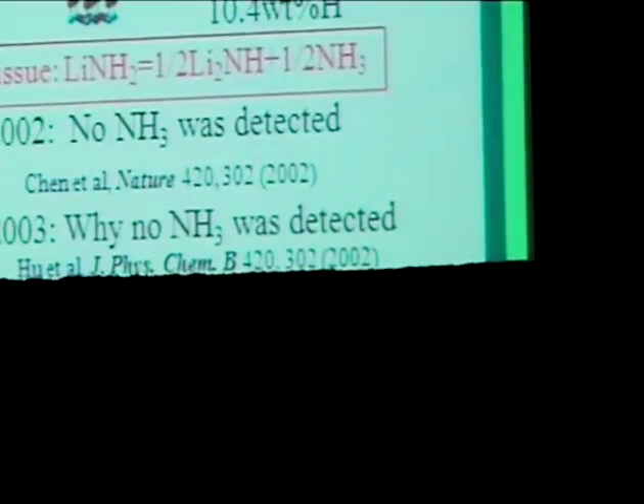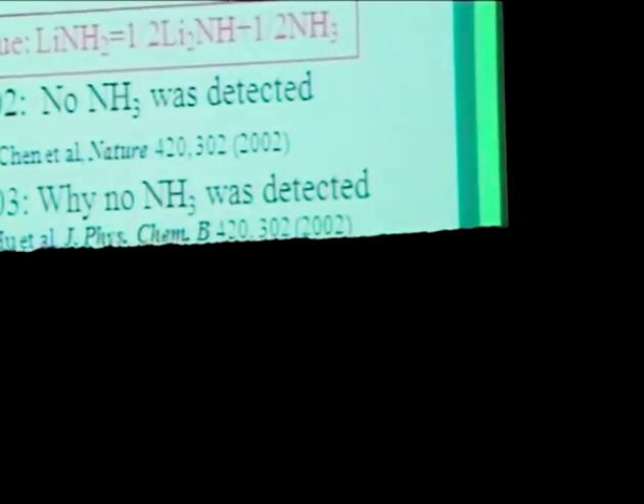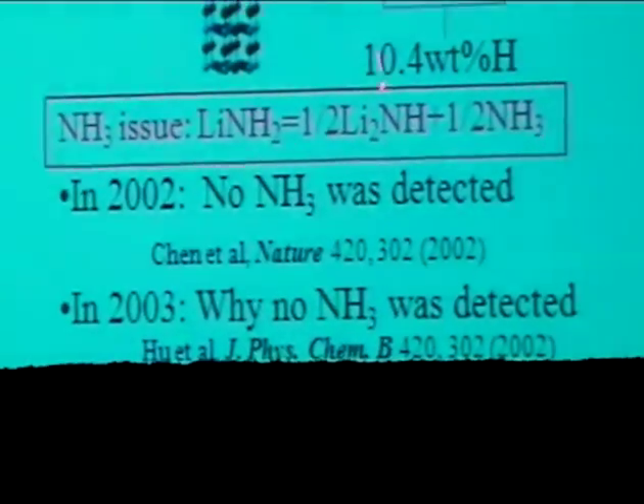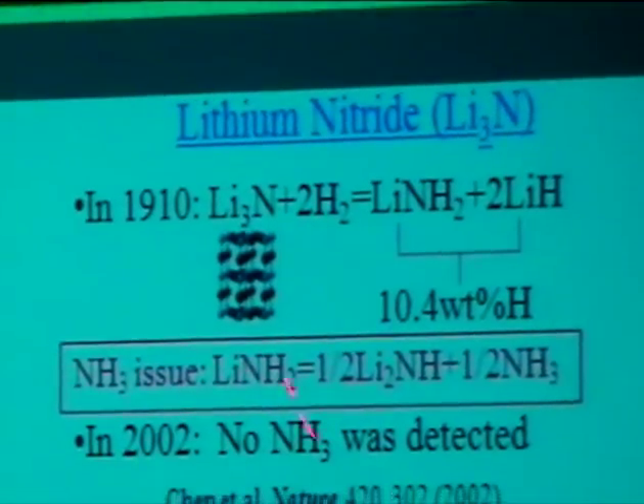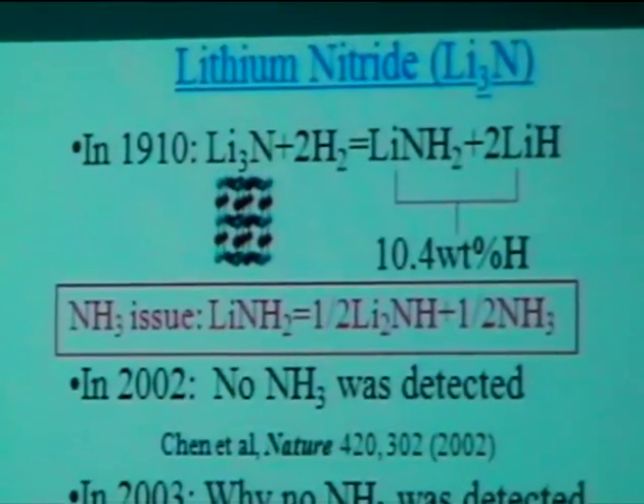So that's like the review. The reviews for this Nature paper gave totally different comments. Some said this is very important. Some said it did not provide the science, but Nature published the paper because they would like to bring attention to this material. The most important contribution of this paper is that there was no ammonia detected during dehydrogenation. They said it has the potential to give ammonia, but they didn't detect ammonia. So in 2003, we did the experiment to find out why you didn't get the ammonia. The reason is that you formed lithium hydride. Lithium hydride can capture ammonia, so you have no problem with ammonia.